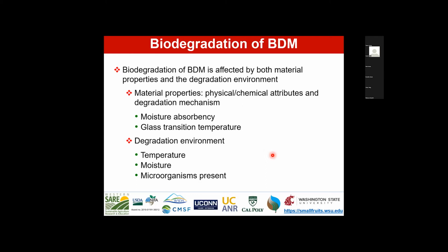So let's spend a little bit more time talking about biodegradation of biodegradable plastic mulches. It is affected by both material properties of the film itself and then the degradation environment. The material properties include the chemical and physical attributes and the degradation mechanisms specific for that material. Things such as moisture absorbency and glass transition temperature are essential for that. Glass transition temperature is essentially the temperature where the film transforms from a rigid glassy state to a flexible state that is more accessible to microorganisms to break it apart through that degradation process. Then the degradation environment is also important. Things such as temperature, moisture, as well as the microorganism community present will influence biodegradation of biodegradable plastic mulches.